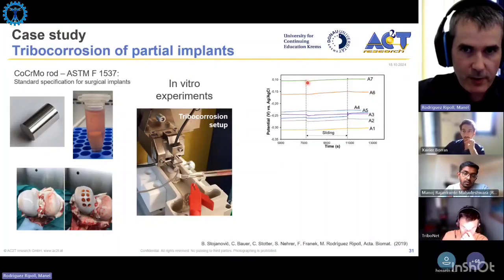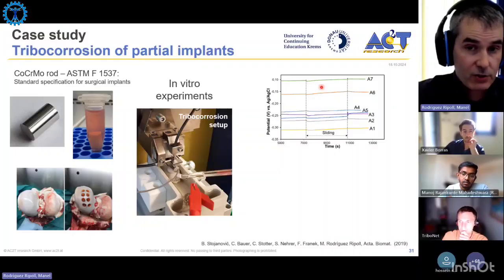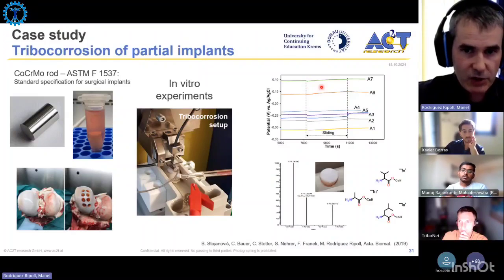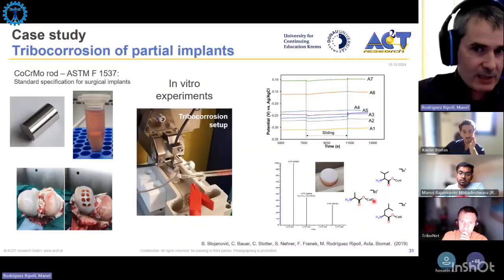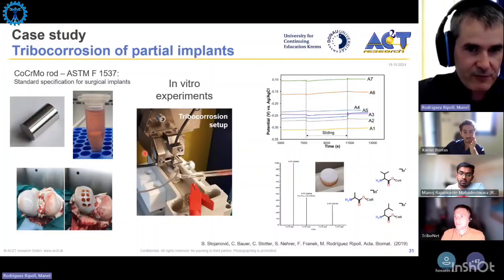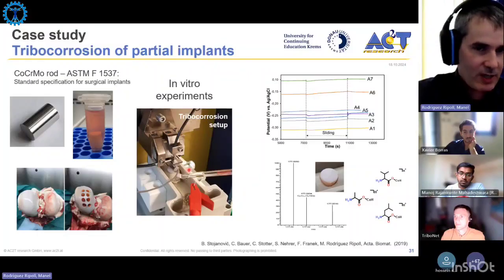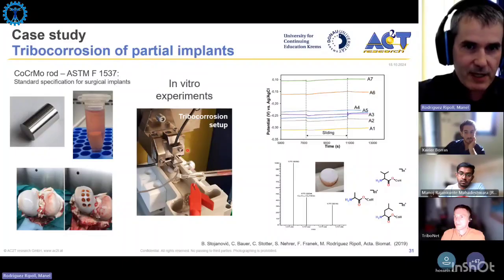And this drop of OCP means that we are having metal release, so cobalt, and we could also check, for example, using high-resolution mass spectrometry, that this cobalt was found to be bound to amino acids. So you can also use these tribocorrosion methodologies with in vitro setups for tracking biomedical implants or evaluating the performance of biomedical implants in vitro.